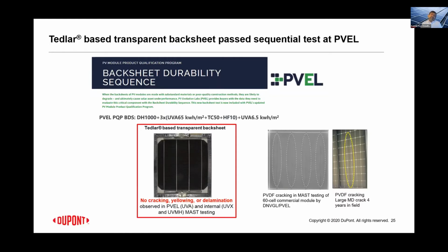So this again gives us the full level of confidence that even in accelerated testing, sequential accelerated testing, this particular material, which is a rather new entrant in the field, in the bifacial market, should be holding up for its entire lifetime and performing as expected over 25 to 30 years.